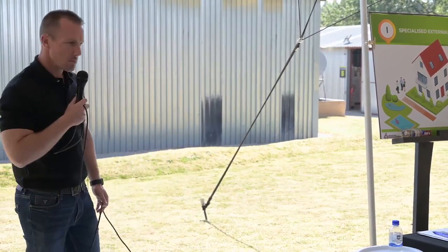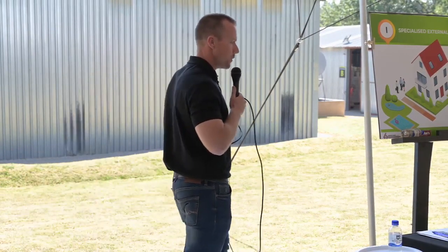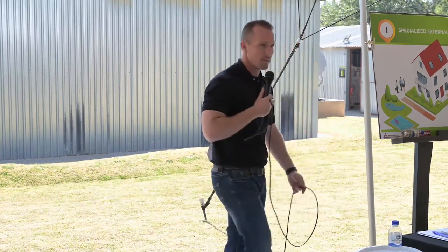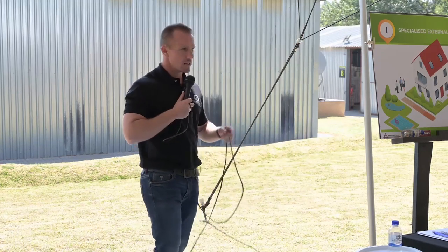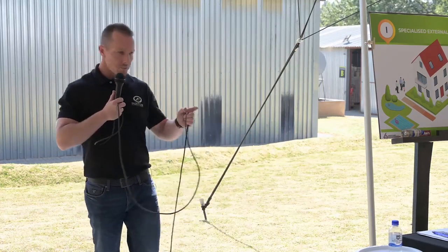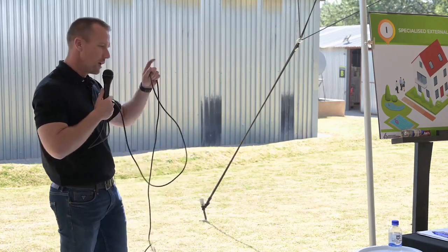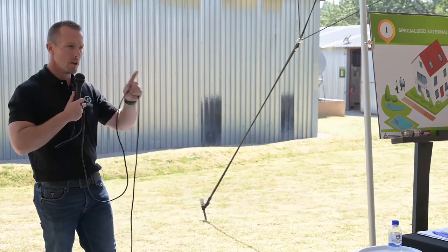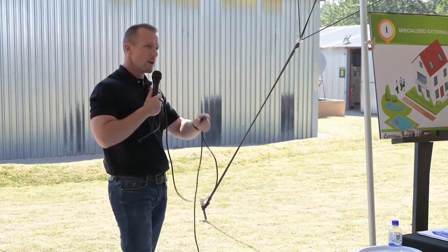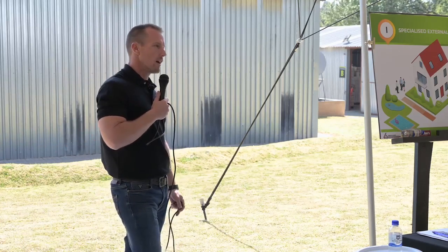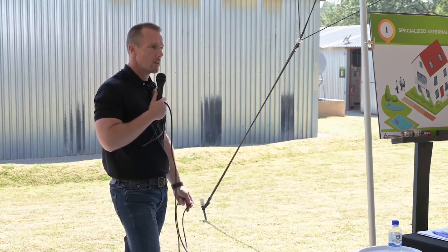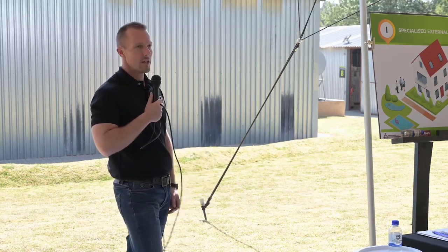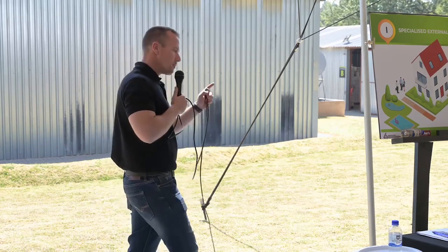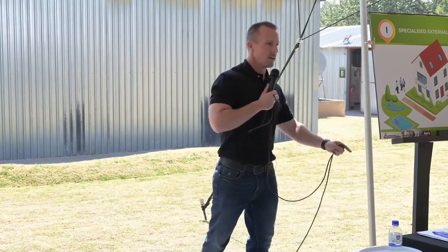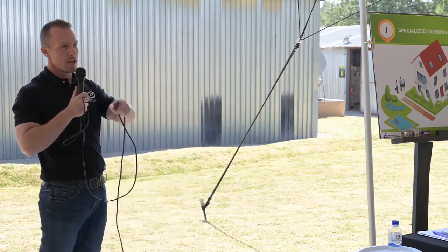I'll give you an example of where it can be used effectively. Let's say you have a plumbing issue in a client's house. You've identified that the plumbing is coming from the pipes, let's say in a shower. You chop off the tiles, chop out the plaster, identify where the leaking pipe is. You make good the pipe work, seal it up, replace the pipe where necessary, then you replaster. Now ordinarily you would leave site for a week or 2 weeks, and come back when the plaster's dry, retile, eventually get paid and make your way out. What Cementec will allow you to do is plaster today, apply Cementec today, come back tomorrow to do your tiling and get paid by Friday.